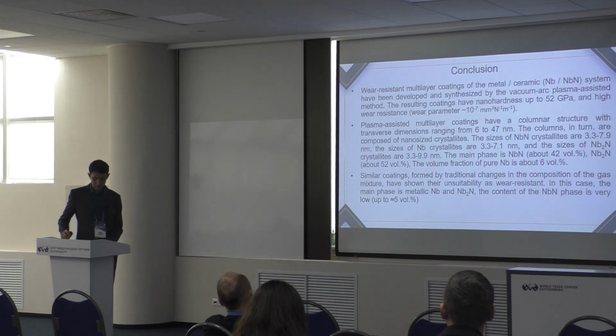In conclusion, using the example of a niobium nitride coating, the rationality of using the low-inertia plasma-assisted vacuum deposition method for the formation of multilayer superhard coatings with high wear resistance is shown.